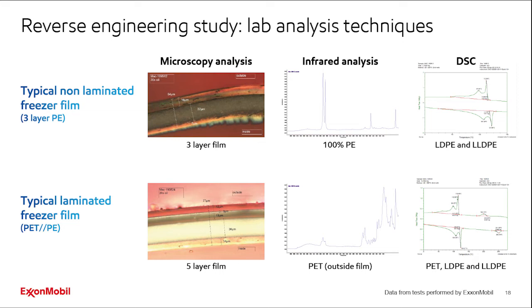And then the third and last technique, DSC. DSC stands for differential scanning calorimetry. It's a very complex name, but it's a thermal analysis. In that case, we measure the amount of heat required to increase or decrease the temperature of the freezer film. And then we compare that data with a reference. And we can go even further. For instance, with the infrared, I've just said we can identify whether we have PE in the freezer film. And with DSC, we can even identify the polyethylene product subfamilies, for instance low density PE can be identified with that technique.